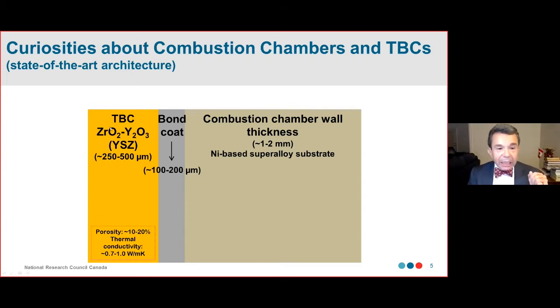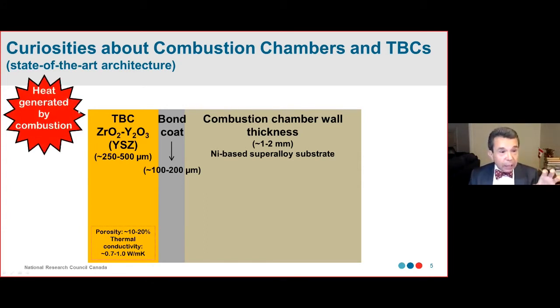Just to have an idea, the melting point of this material is 2,700 degrees Celsius, while the melting point of the nickel-based alloys is between 1,300 and 1,400 degrees Celsius. So we need a very high temperature material to allow a very high combustion temperature. And talking about combustion temperature, we know from the film that you have the heat generated by the combustion. What is the maximum limit that TBCs are working at right now? The maximum limit is about 1,300 degrees Celsius that these TBCs are seeing right now.